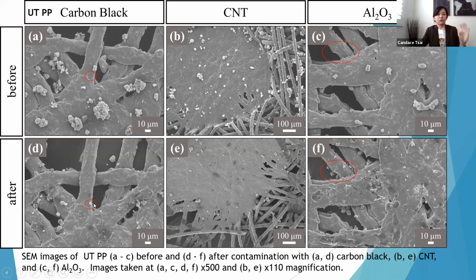Because we found those particles after shaking, they disappear. You can see it on the second one for the aluminum oxide - there's a lot of shadow here, so those are the particles. So we found many, regardless of different size, small or big, they can all be shaken off.